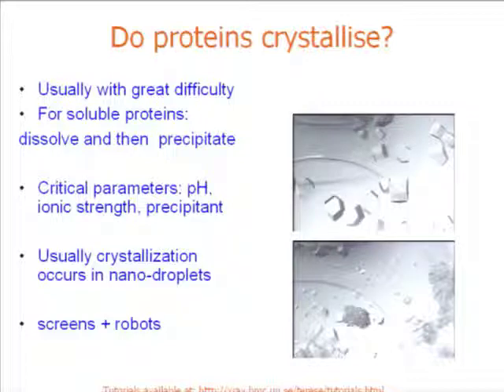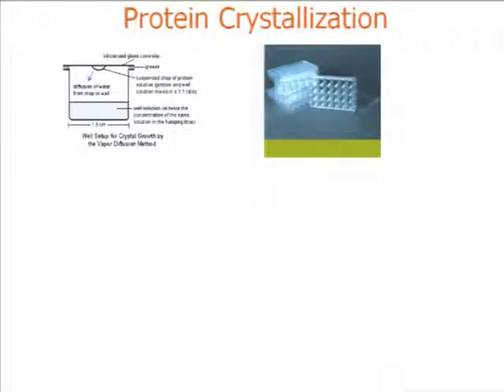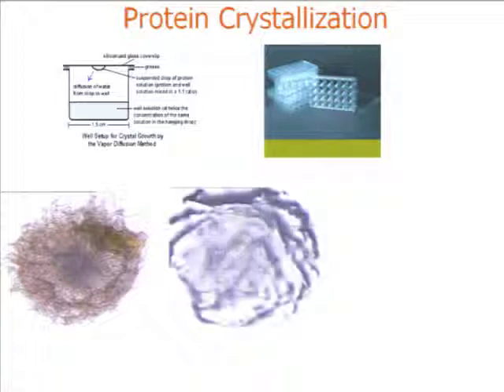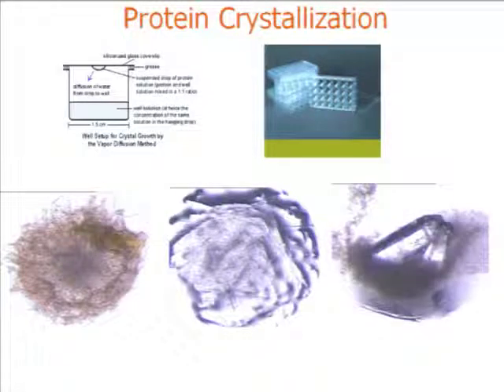We use crystallization robots and screens nowadays, and crystallization can occur in nano droplets in order to minimize the amount of protein used. So if someone gets a single crystal like this, they do a single crystal experiment. But if you have something like this, this is a powder, and this is why powder diffraction was introduced in the protein crystallography field originally. So if we are at the right crystallization conditions, we use plates which are shown here. At the first stage we have precipitate, which is dark, and this is amorphous. Then, if we are lucky, the precipitate crystallizes, and this can be used in a powder diffraction experiment, and with time, a single crystal may grow.